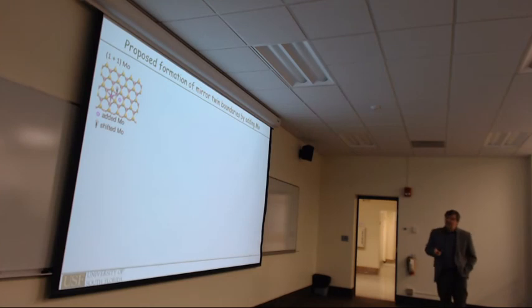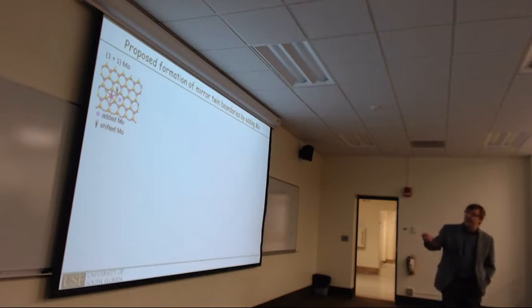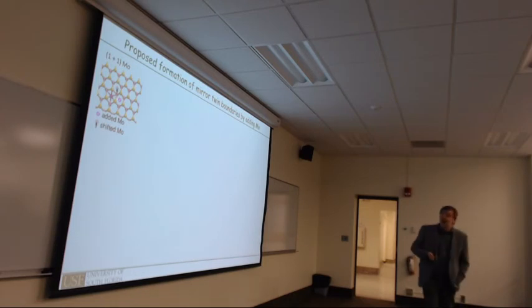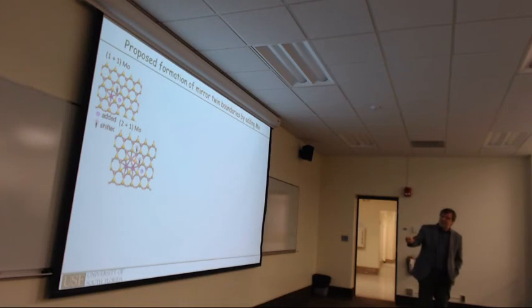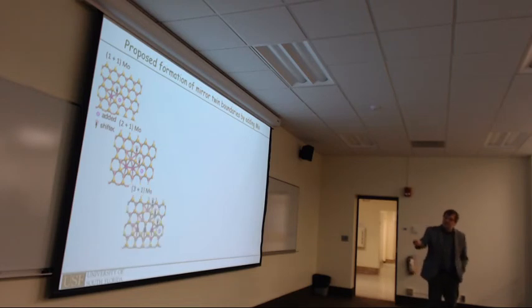So they took it a little further and started by adding 1 molybdenum atom at a time to molytelluride. So we had the first molybdenum likes to be in the interstitial site. You add the second molybdenum, it goes also into an interstitial site neighboring it, and pushes 1 molybdenum atom out into the next site. So then you have this cluster of interstitial molybdenum. You add the third molybdenum, which goes here, and then it pushes those molybdenum atoms over, and then you already start seeing the nucleation of a twin grain boundary, adding a 4th molybdenum atom and make it grow.